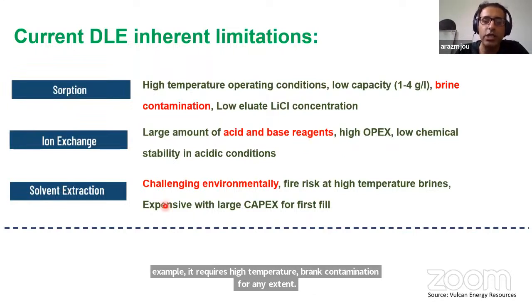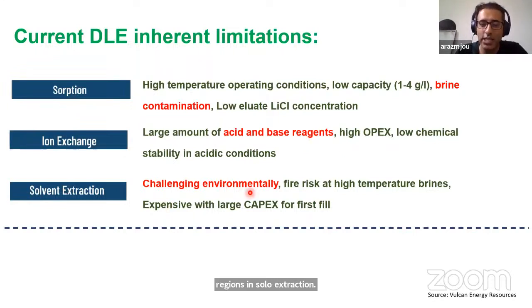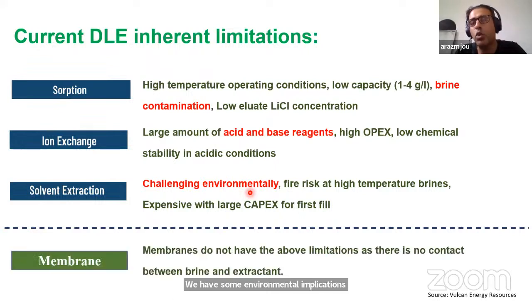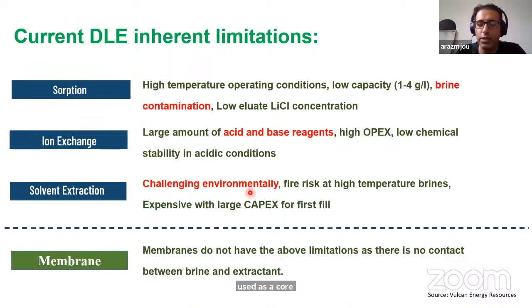In solvent extraction, we have some environmental implications, whereas for membranes, we don't have that sort of issue. That's why membranes are so attractive these days to be used as a core technology for DLE. And the main reason is because there is no contact between brine and extractant.